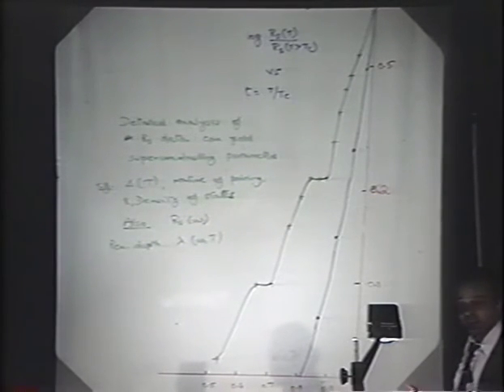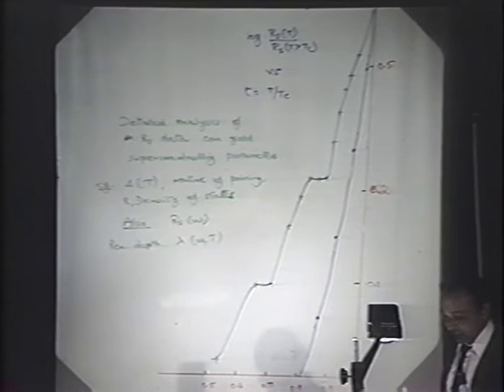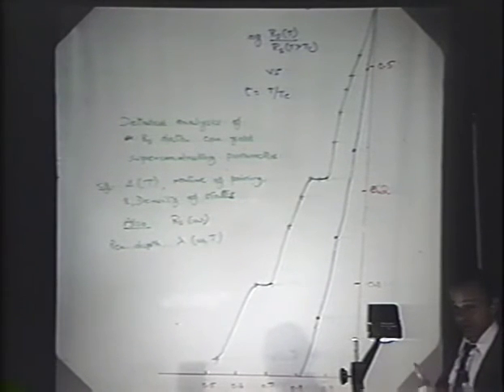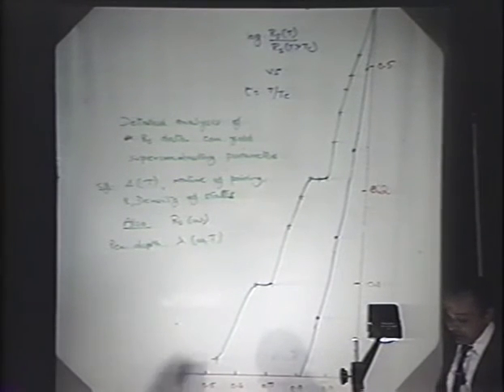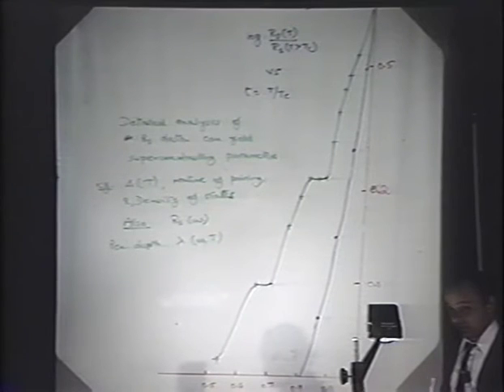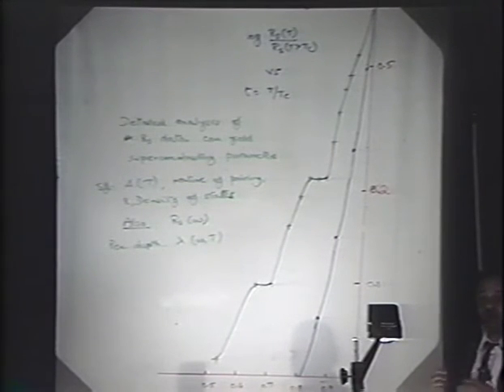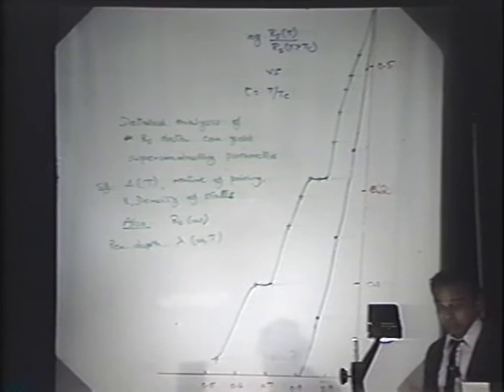Now, overall, my first impression is that this lanthanum strontium copper oxide material looks pretty much like BCS. The deviations may be ascribable to the fact that the transition is actually broad over a couple of degrees at least, whereas tin shows an extremely sharp transition. In addition, we see some steps here, which may be due to, I've heard, grain boundaries having slightly lower TCs. The point is that whereas the DC measurement shorts out when the first superconducting network forms, the microwave measurement is sensitive to the normal absorbing parts, and that kind of information comes out of this.